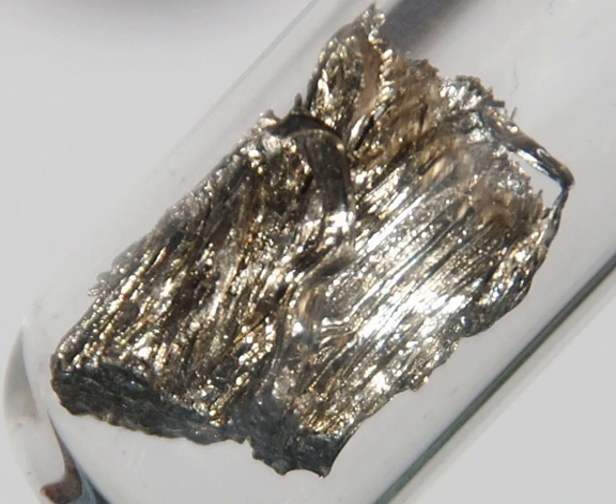Heating the metastable trigonal Sm2O3 to 1900 degrees Celsius converts it to the more stable monoclinic phase. Cubic Sm2O3 has also been described. Samarium is one of the few lanthanides that form a monoxide, SmO. This lustrous golden yellow compound was obtained by reducing Sm2O3 with samarium metal at elevated temperature, 1000 degrees Celsius, and pressure above 50 kilobars. Lowering the pressure resulted in an incomplete reaction. SmO has the cubic rock salt lattice structure.